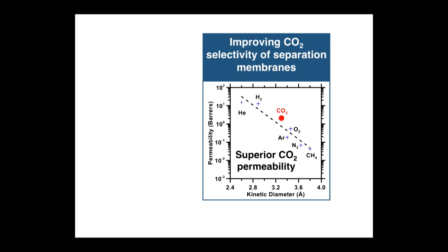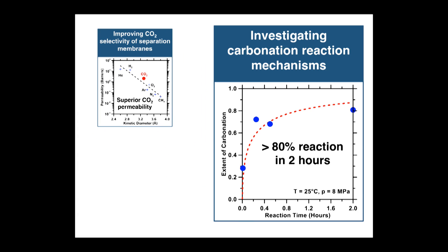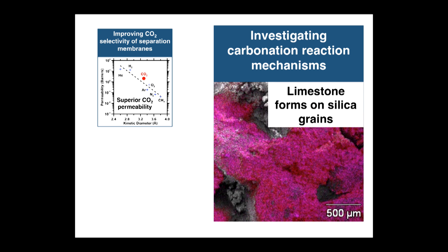Dr. Bu Wang and I have been focusing on investigating the actual mechanisms of the carbonation reaction by which CO2 is incorporated into limestone. We have found the reaction to be quite rapid, reaching over 80% completion within two hours, and also found that it can provide strength. This is a SEM image that shows limestone colored in pink based on its elemental analysis, and you can see that it's forming on silica grains in a cohesive layer. This could provide strength in binding aggregates, the way normal cement does in concrete.